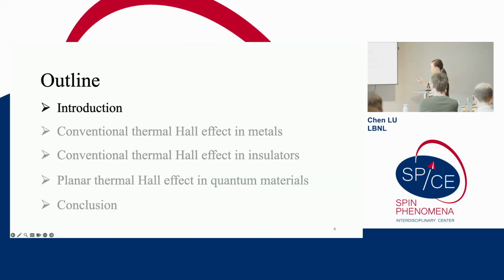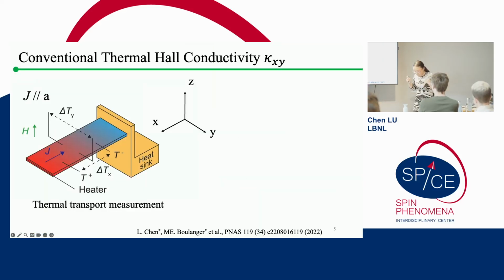So let's first take a look at what a thermal Hall effect measurement is and how we perform the experiment in reality. The figure here shows the schematic of our measurement setup. Usually for this type of so-called thermal transport measurement, we have a very thin, plate-shaped, rectangular sample, and you glue one end of the sample on a heat sink, which is usually made of copper or lithium fluoride, some non-magnetic material. And on the other end of the sample, you put a heater. The heater is used to generate a thermal gradient along the sample.